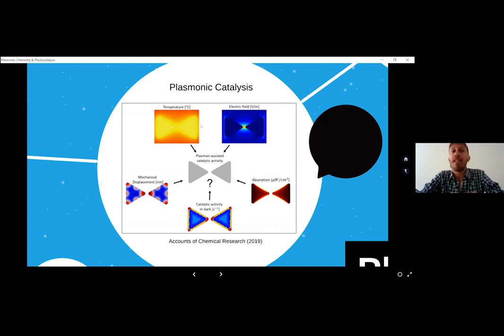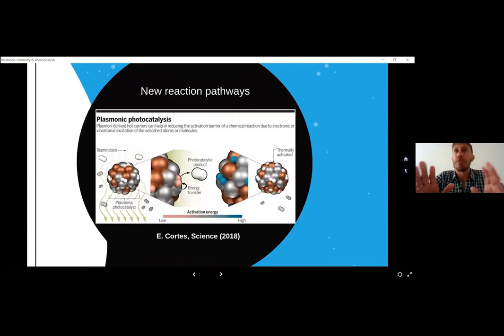So the idea is, can we use these materials in order to absorb light, ideally sunlight, in order to drive chemical reactions in a cleaner way and in an energy safe way. And besides this, there is also something else behind, and it's the idea of how we compare this type of reactions with thermal activated reactions. So nowadays in industry, most of the reactions that involve a catalyst, right? So heterogeneous catalytic reactions are driven at really high temperature, at really high pressure, right? So that's the way in order to trigger reactions. So we have a material that sets an activation barrier for the reaction, and then we need to increase the temperature or the pressure in order to achieve the conditions in which we can overcome the activation barrier of the reaction and generate products.